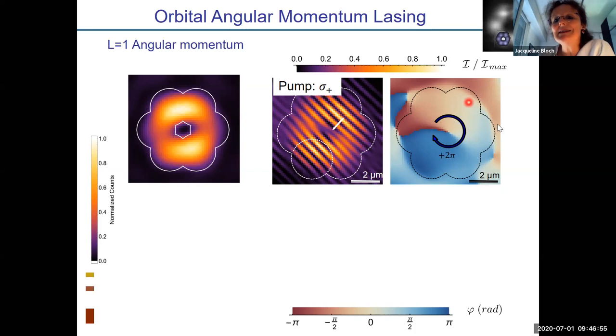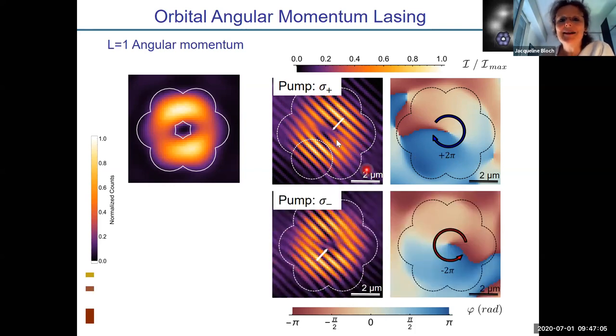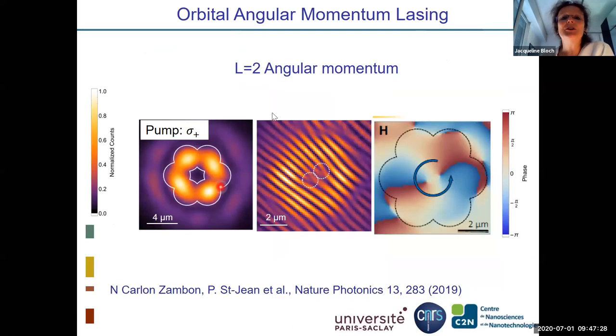And you see that the phase is indeed rotating, and we get an accumulation of 2 pi when we make a 2 pi rotation. Now, if we pump sigma minus, you see that this pitchfork dislocation is on the other side, and you see that the phase is rotating the other way. So we have here an orbital angular momentum of plus 1, or plus h bar, and here minus 1, and we can control this helicity just by the polarization of the excitation beam. Now I show you another molecule where the gain is larger for the L equal 2 manifold. And here you see under sigma plus pumping, you now have 2 pitchfork dislocations, and you see that the phase is rotating by 4 pi.